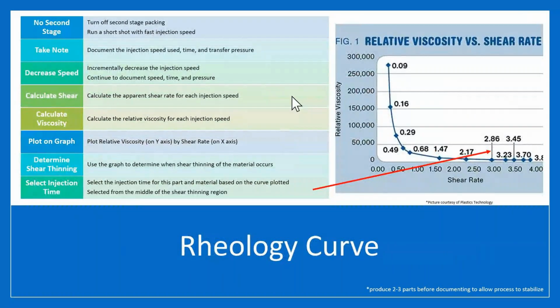From there, we're going to perform a rheology curve. This is also called in-mold rheology, or an in-mold viscosity curve. But what we're essentially doing is getting a relative viscosity and relative shear rate so that we can capture the shear thinning of the material in our specific machine and tool.